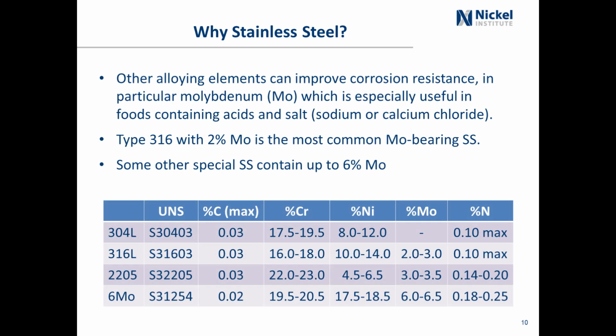Other alloying elements can improve the corrosion resistance, in particular molybdenum, which is especially useful in foods containing acids and salts. And you probably have examples of that you've seen in your own work. Type 316 with 2% molybdenum is the most common of the moly-bearing stainless steels. Some other special stainless steels contain up to 6% molybdenum.